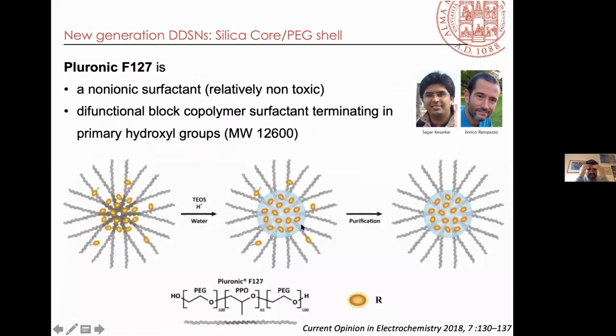So we started this story with an approach of nanoparticle synthesis that was very novel, I think, at that time. This synthetic approach is micelles induced synthesis of nanoparticles. So basically we use pluronic surfactant. Pluronic surfactant can generate micelles in water solution, and you use this micelle as a template for the synthesis of the nanoparticle.